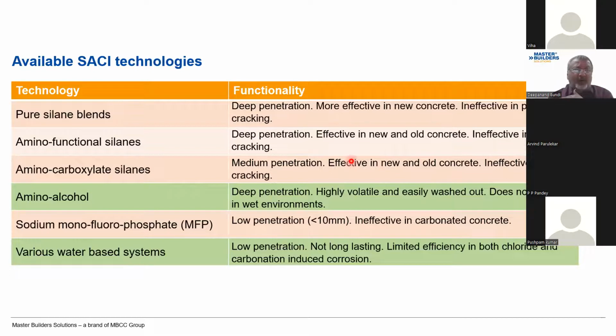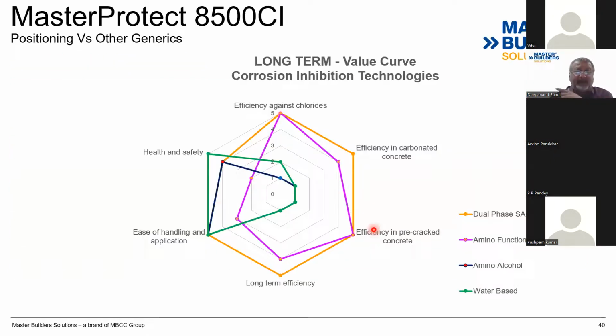Now, in terms of all these technologies that are available, when you compare it with a dual phase surface applied corrosion inhibitor, it definitely is by far much more efficient against chlorides, carbonated concrete, and efficiency in pre-cracked concrete. So even if your concrete is cracked, you will have very good protection, long-term efficiency, ease of handling, and health and safety. So if you compare it with amino functional silanes, amino alcohol silanes, or water-based protections, you will always have a better edge in terms of performance of these coatings.